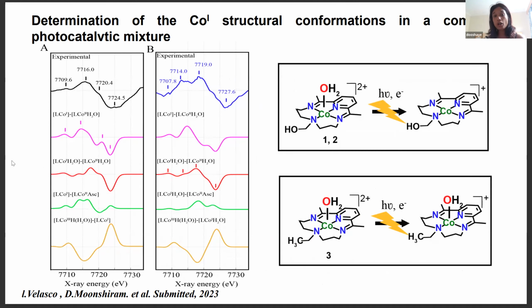We also were able to corroborate the structure of the photoreduced cobalt-1 intermediate by comparing our experimental spectrum with the TDDFT calculations of various candidates. So we did these calculations, my students and I, through ORCA, and the best agreement for complexes 1 and 2 was that of a square planar geometry, which has been shown to be the typical geometry for CO2 or proton reduction intermediates, whereas that for catalyst 3 was that of a square pyramidal cobalt-1 geometry. And both geometries have been shown to be involved in the CO2 or proton reduction reactions.